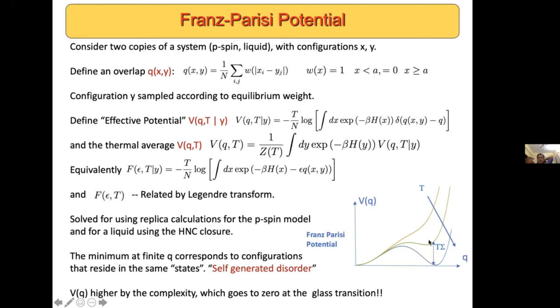But that event is less probable as compared to them being completely dissimilar by a cost which is given by the complexity. And therefore, the height of the second minimum at any given temperature is the complexity, and this is a way of measuring it. And when that height goes to 0, as shown in the lowest curve, one reaches the ideal glass transition. And this has been used as a way of introducing self-generated disorder and to evaluate the glass transition.